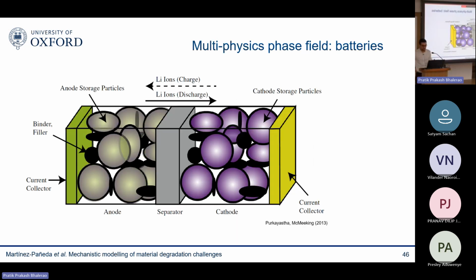The mechanisms are quite simple when it comes to degradation mechanisms. Every time you charge your battery, you have lithium ions going from these cathode particles to these anode particles, and every time you discharge your battery, you have lithium ions going from the anode particles to the cathode particles, and then electrons going the other way around.